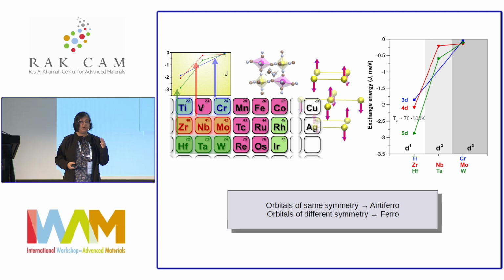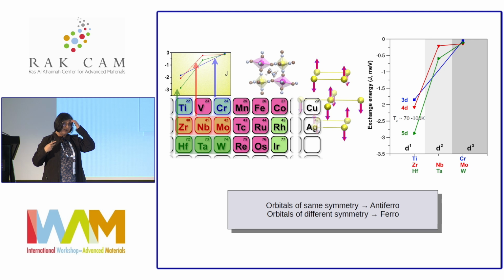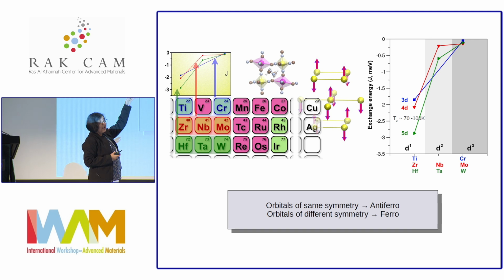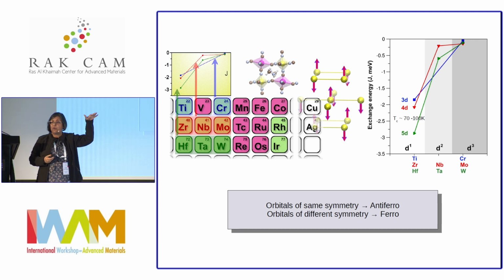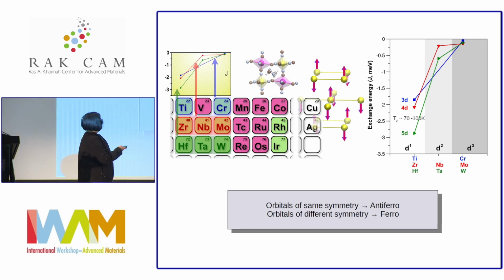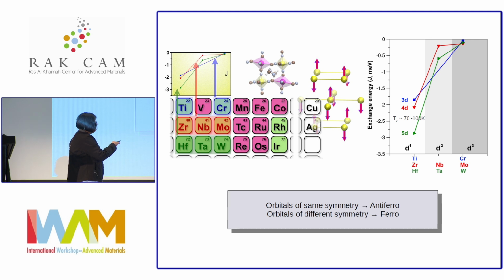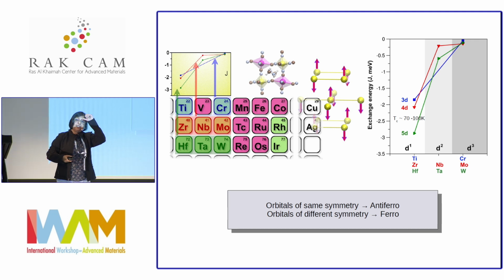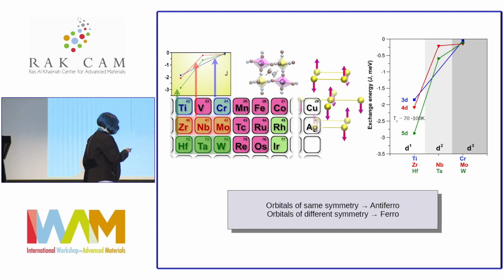In case of D2, two different orbitals of two different symmetry are populated, and therefore you have a competing ferro-type interaction that basically competes with the antiferro. So both the ferro and antiferro channels open up, and what you see is that the net interaction, although it's antiferromagnetic, gets weakened by the competition from the additional channel, which is ferromagnetic. And we calculated the mean field TC. This is a mean field estimate, but still the TC, which is actually the TN since it's an antiferromagnetic order, is about 70 to 100 Kelvin.